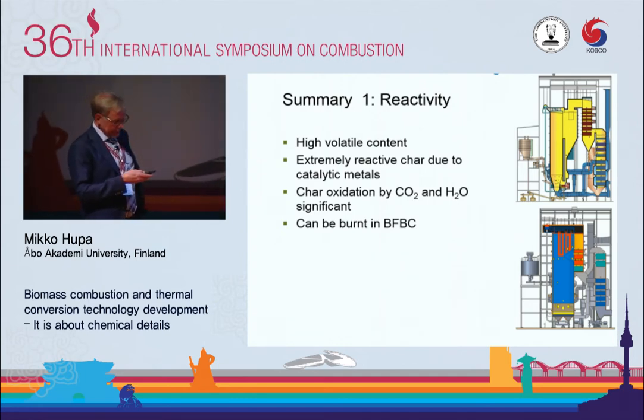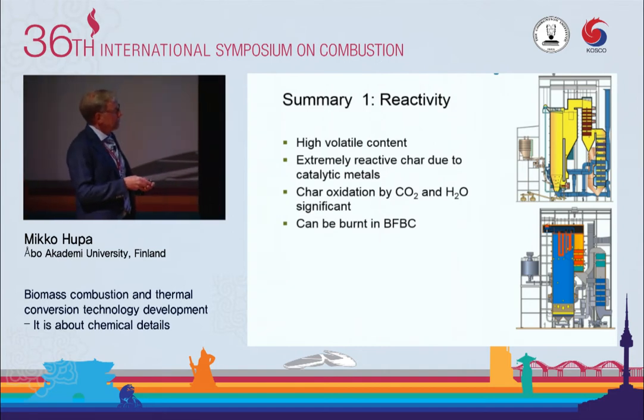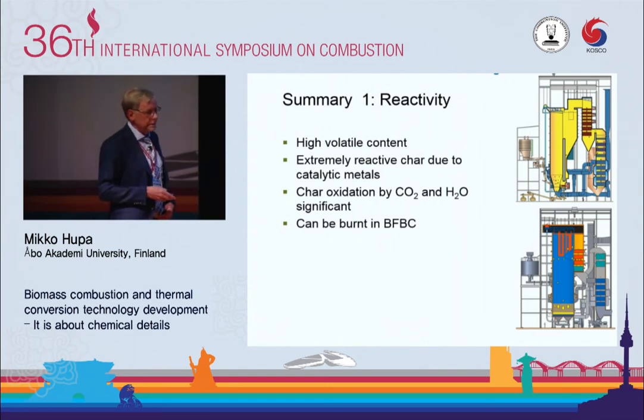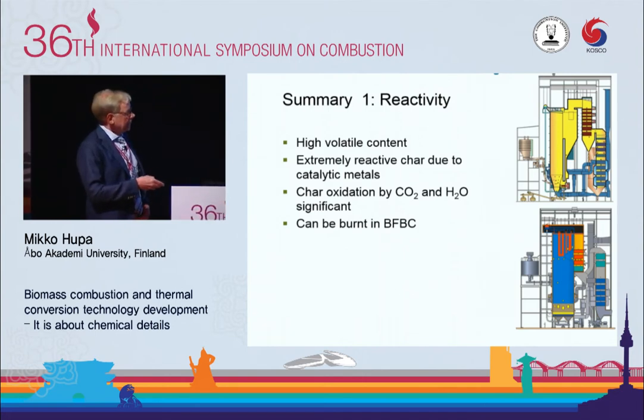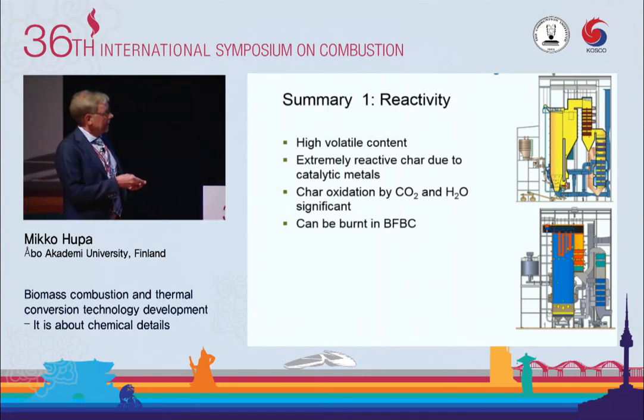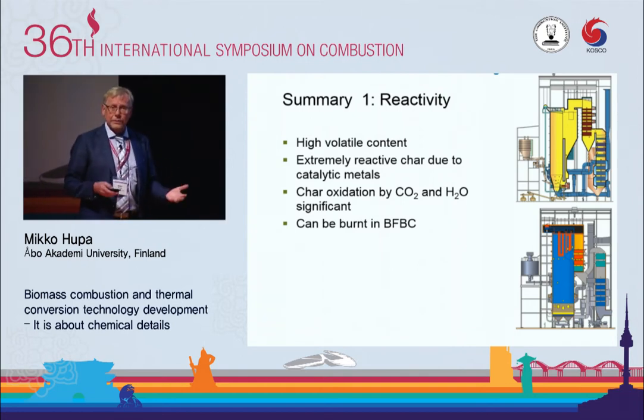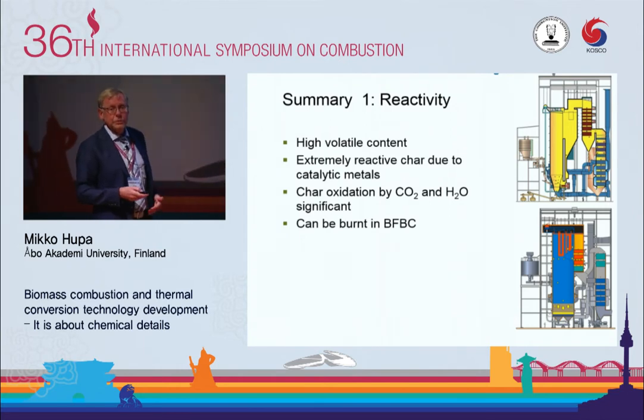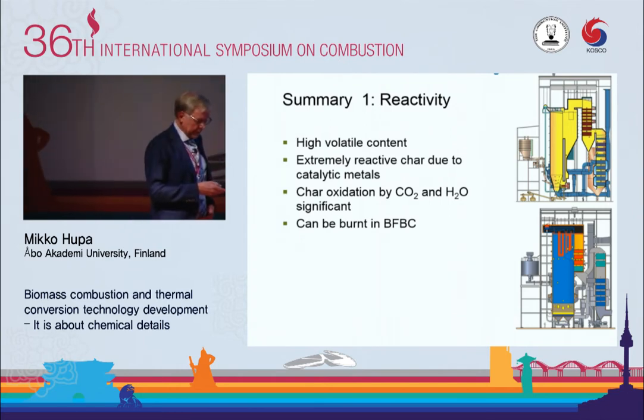It is that since the char is so reactive, that explains why we can burn biomasses using the bubbling fluidized bed technology, where all the char combustion takes place here in the bottom of the boiler, instead of going to the circulating bed where the char particles have a long residence time in the circulation. This is needed for coal because of the char unreactivity. But here we can burn. This is much more simple. This is a less expensive solution. In fact, the bed itself here in the bubbling bed is slightly reducing, so there is not very much oxygen there. So the char conversion mostly takes place by CO2 and water vapor gasification.